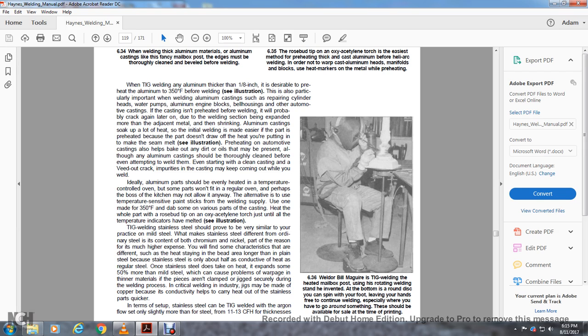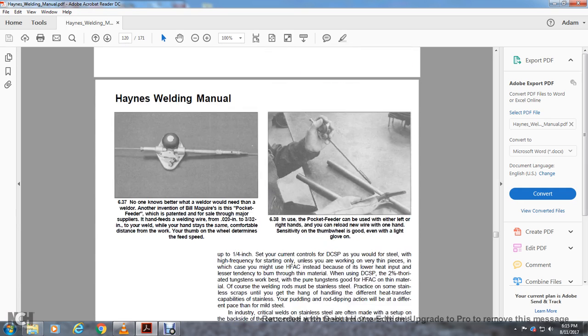Alright, once set up, stainless steel can be TIG welded with the argon flow set only slightly higher than for steel, at 11 to 13 cubic feet per hour.